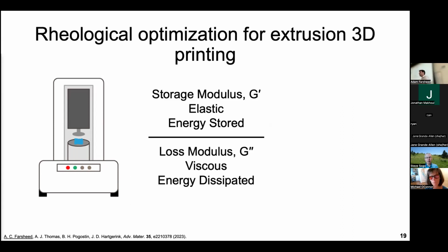And by varying aspects of that rotation, we can understand the two main things about our material. The first being understanding the storage modulus, which we can think of as the elastic component of our material, and it's actually the energy that's stored in the bonds of our system as it's deformed. And the second being the loss modulus, which is the viscous component of that material. And you can think of it as the energy dissipated, usually in the form of heat, as you apply a force to it. And so the storage modulus, to simplify, I think of it personally like the solid-like component, and the loss modulus like the liquid-like component.